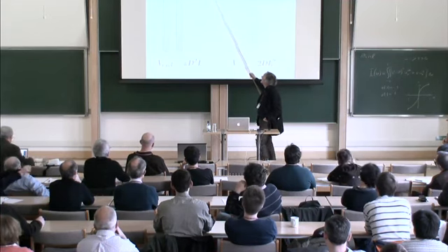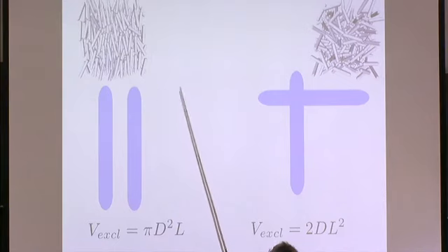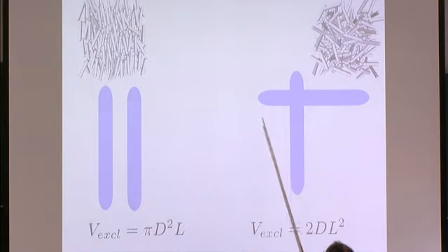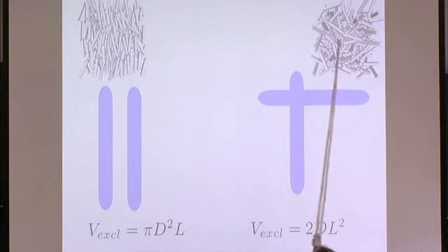and therefore they have a higher entropy. And so the higher translational entropy, they pay for it by lowering their orientational entropy, but at some point that trade-off becomes favorable, and you go from the low density isotropic phase to the high density nematic phase. That is in words what happens.